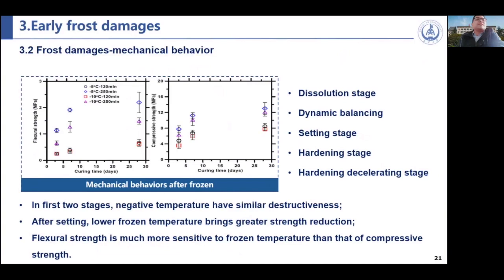In the first 2 stages, we also measured the frozen temperature effect on the performance of the cement paste. In the first 2 stages, the negative temperature has similar destructiveness with others. After setting, lower frozen temperature brings greater strength reduction. You can see from here, from this blue part. And also the flexural strength is much more sensitive to the frozen temperatures than the compressive strength.